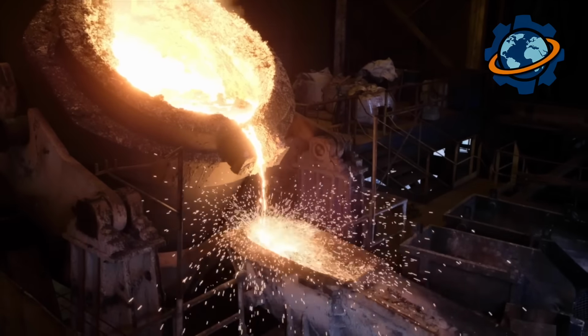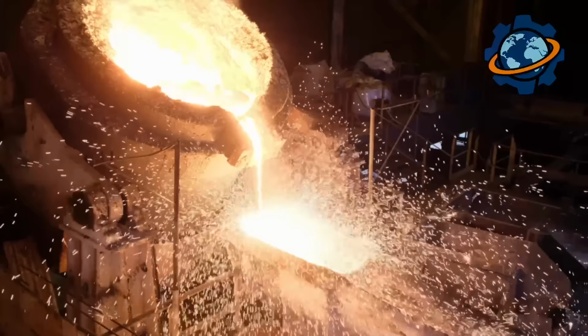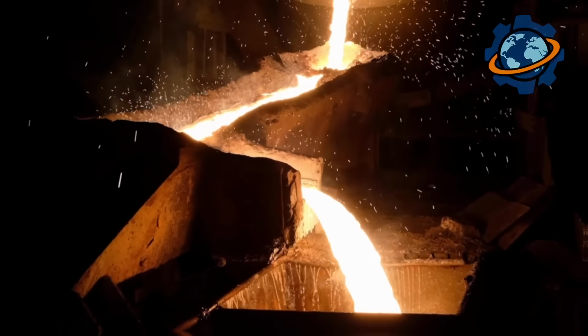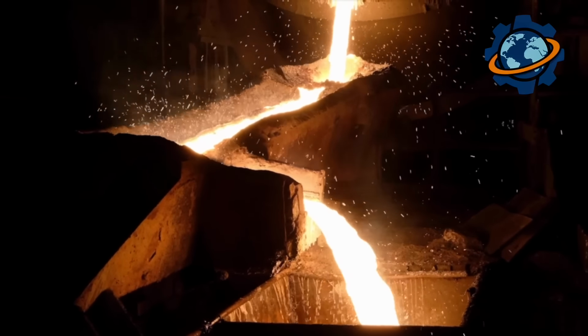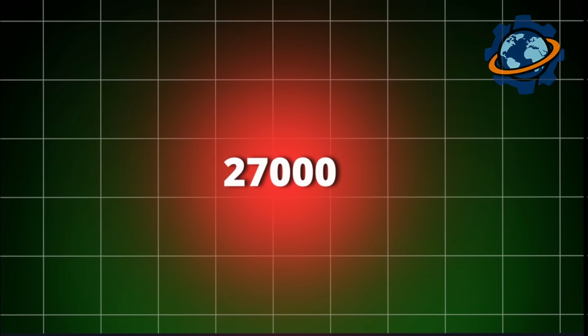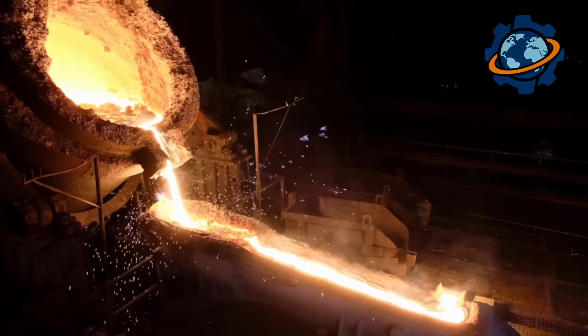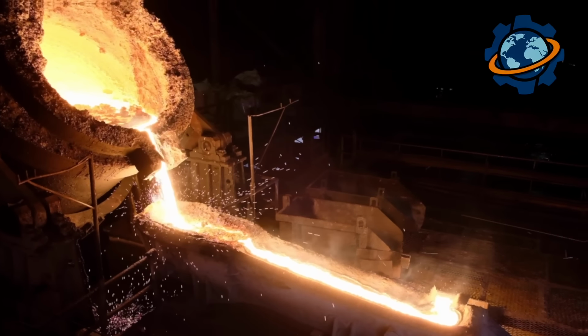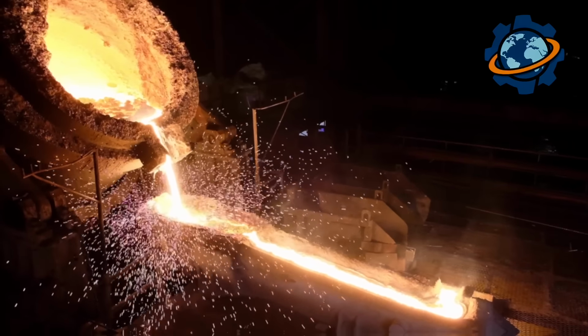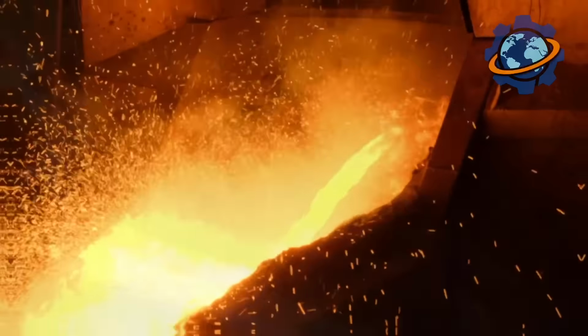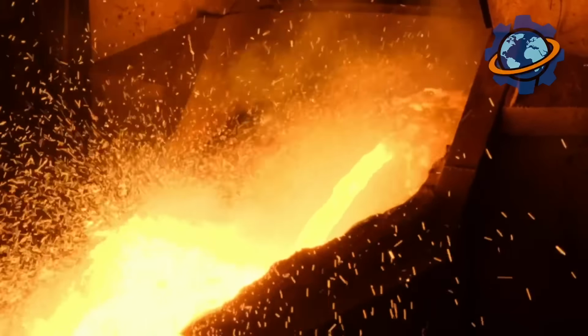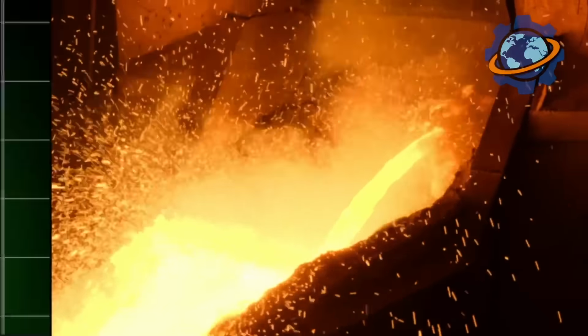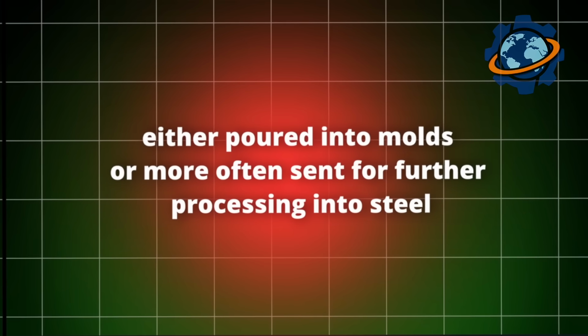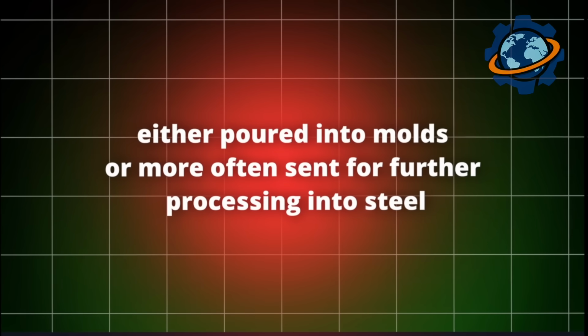And then they open the iron tap hole, and a dazzling, sparking stream of molten metal erupts with a roar. This is the River of Fire. The temperature of this stream is around 2,700 degrees Fahrenheit, 1,500 Celsius. It flows down special troughs, bathing everything around in a blinding light, and fills giant ladles that look like railway tankers. Each of these ladles holds hundreds of tons of liquid metal. From here, the pig iron will be sent to its next stage, either poured into molds, or, more often, sent for further processing into steel.